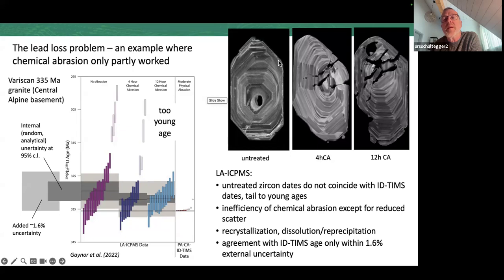These are alpine rims by physical abrasion. I learned many years ago from Don. And then we do not manage to get rid of this, because when we do chemical abrasion, these are perfectly crystalline, but alpine age probably. So this is a case, I would say, where we totally fail with our chemical abrasion approach. And it's just another message that it's really worth it to look in detail at the CL images. Even only qualitatively, you can get an idea what you see.